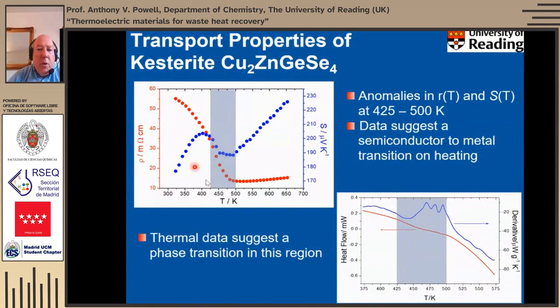It appears to show in this region here what has been referred to as a semiconductor to metal transition on heating. So here's the resistivity, clearly semiconducting behavior, and then it turns around and starts to increase. So the Seebeck shows anomalies as well. And also we find that DSC data show quite significant changes in slope in that region, which maybe show up more clearly if we take the derivative of the heat flow. But nonetheless, we have something going on in that region where we have quite marked changes in electrical properties.